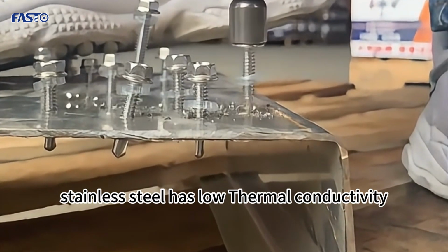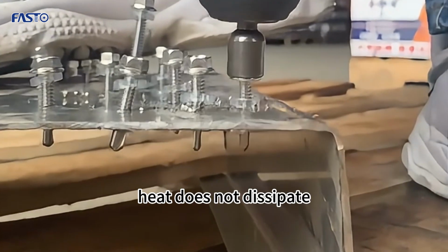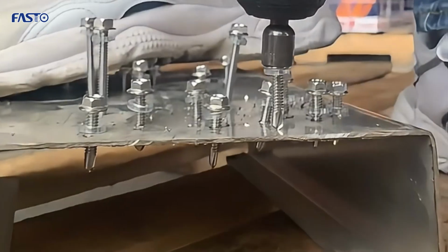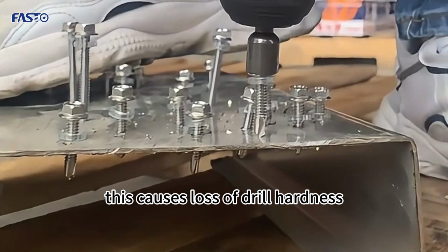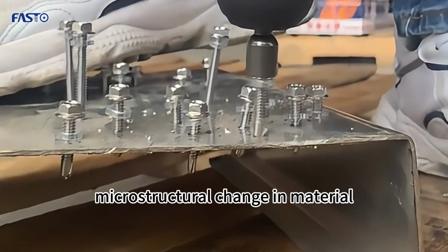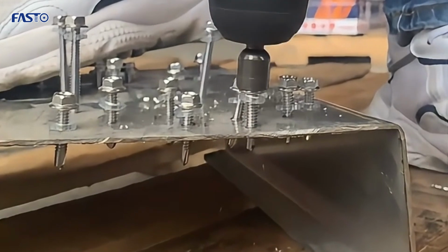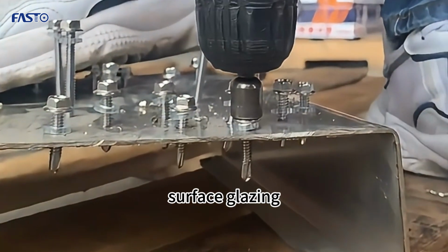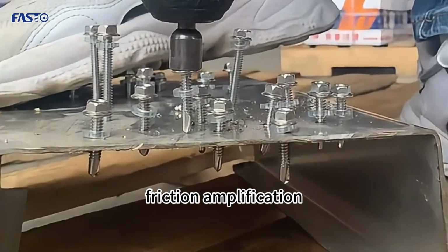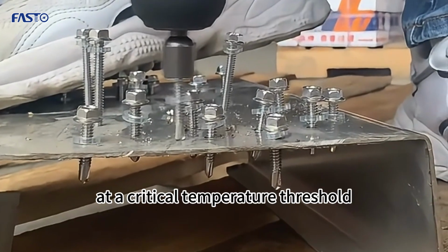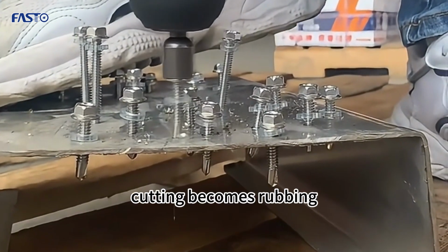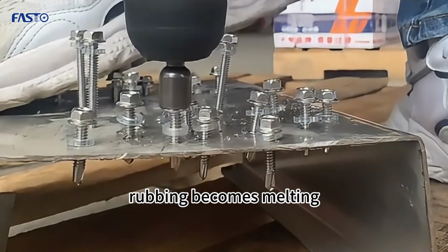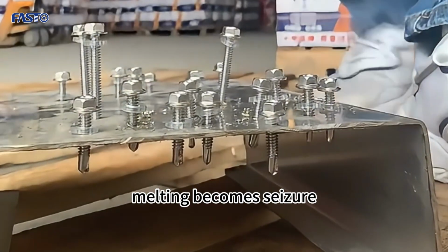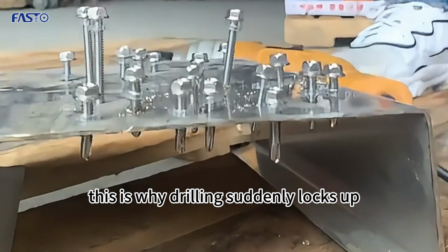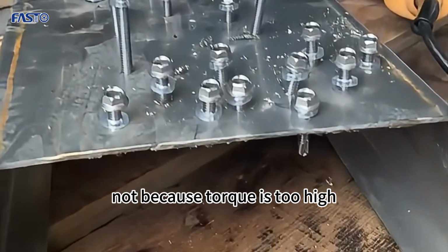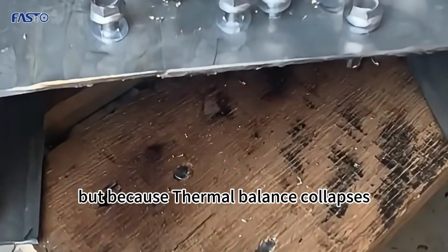Stainless steel has low thermal conductivity. Heat does not dissipate, it accumulates at the cutting zone. This causes loss of drill hardness, microstructural change in material, edge softening, surface glazing, chip welding, friction amplification. At a critical temperature threshold, cutting becomes rubbing, rubbing becomes melting, melting becomes seizure. This is why drilling suddenly locks up, not because torque is too high, but because thermal balance collapses.